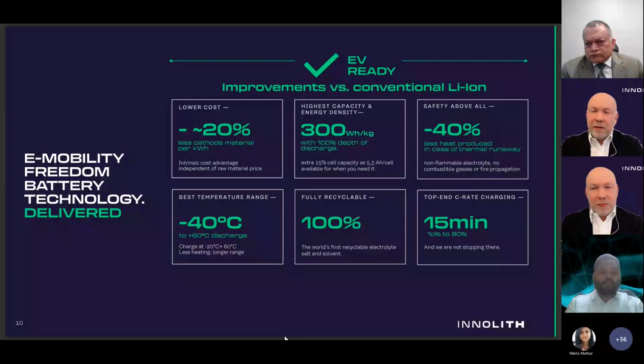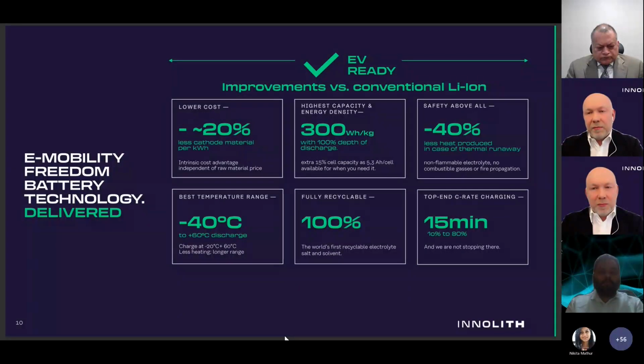Safety is increased, as I've mentioned in one of the first slides. There is no flash point. The electrolyte is not flammable. When a cell goes into thermal runaway for any negative reason, normally there are two sources of energy. One of them comes from lithium and other materials like the separator, and another one, approximately 50%, is the electrolyte. In our case, the electrolyte does not release any energy, and a 40 to 50% reduction in the energy release means fire propagation is reduced down to almost zero. We've tested it, and it's a very interesting differentiation from conventional lithium-ion technologies.